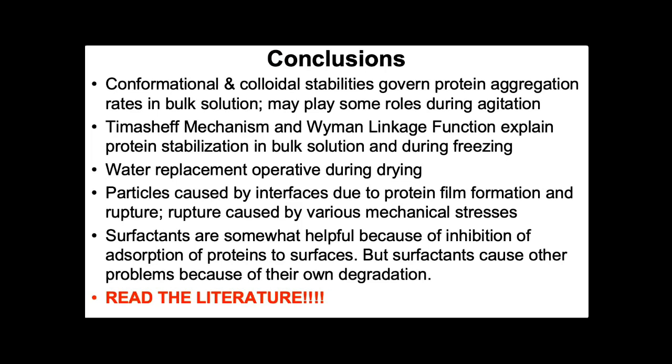And finally, when we have interfaces, interfacial stress, particles are formed because films of the protein form, and any kind of disruption in that film will lead to particles in the bulk solution. And surfactants are quite helpful at inhibiting this, but obviously with modern research we have to be aware that surfactants cause their own problems in particle formation due to degradation. And finally, read the literature. The newest literature is critical to keep up with, and the old literature back even decades ago has very important fundamental information.